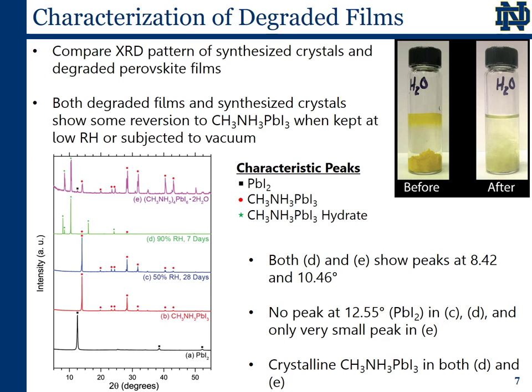Crystals of the methyl ammonium lead iodide hydrate were synthesized by following the literature method and can be seen in the picture at the right. Comparing the XRD patterns of the degraded perovskite films with those of the synthesized methyl ammonium lead iodide hydrate crystals shown in traces D and E respectively, we can see distinct peaks arising at 8.42 and 10.46 degrees, which appear in both of these samples but are not present in the XRD patterns of either methyl ammonium lead iodide itself or lead iodide.